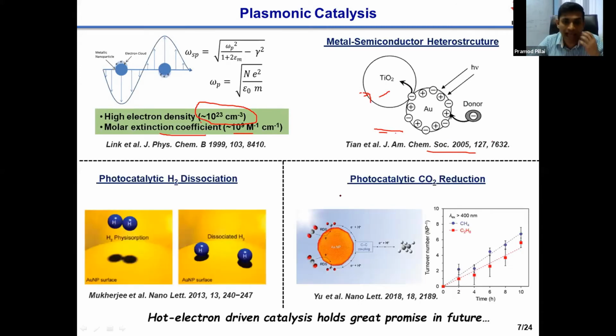But recently, people have started to use plasmonic nanoparticles as a sole photocatalyst for various chemical transformations. So this is an example where the authors have used gold nanoparticle to break hydrogen, which is a very highly energy requiring step, and you can break it with the help of hot electrons. This is another example where people have used gold nanoparticles to reduce carbon dioxide to some value-added products like methane or ethane. So in all these examples, gold nanoparticles are used as a sole photocatalyst.